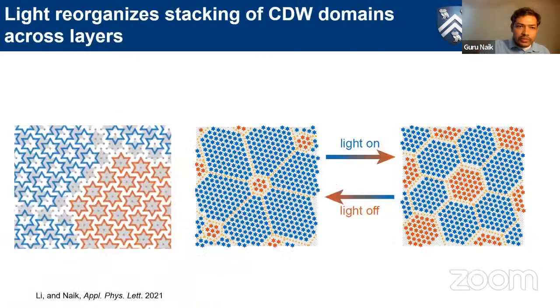Okay. So all of this, in fact, led us to this model, which is that there exist two kinds of stacking, the domains. They coexist at any temperature, whether it's the commensurate phase or the nearly commensurate phase. All of them coexist. So meaning different stacking configurations coexist, and there are domain boundaries, which are shown by these yellow stars. And they really decide how they take away the energy from the photon that shines on this material, and then eventually redistribute or reorganize the fraction of these different stacking domains. So that's the final model that we came up with, which so far explains everything that we have seen.